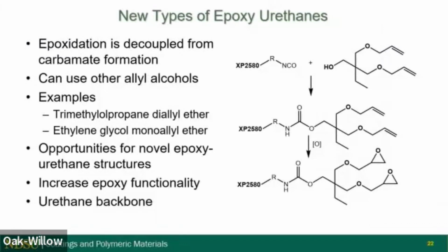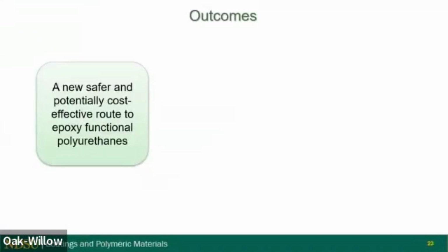It also leads us to a whole new class of epoxyurethanes, because now we're decoupling the epoxy formation from the polyurethane formation reaction. And so we've actually discovered that with these multifunctional epoxies, we can make a compound like this. There's more on the other side that has multiple epoxy groups. And we've discovered that we can cure these systems at very low temperatures as well, because these are really reactive. So again, very good discovery we had with this system.